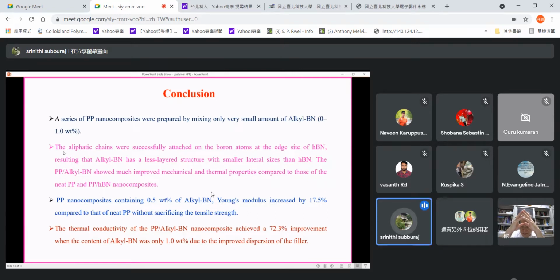So finally, we concluded that the composite increased the Young's modulus by 17.5% compared to that of polypropylene without sacrificing the tensile strength. The thermal conductivity of the preferred nanocomposite also improved when adding the alkyl boron nitride.